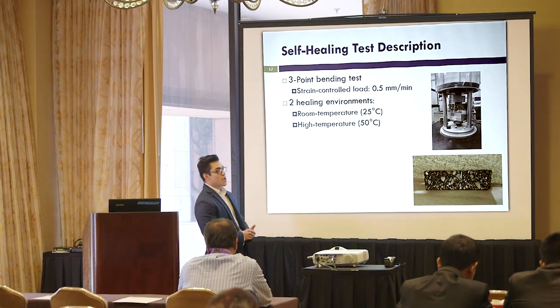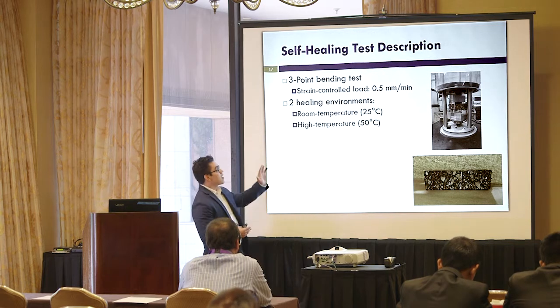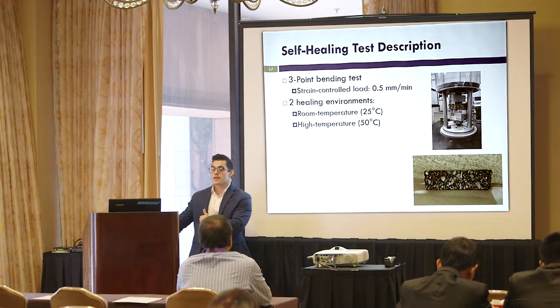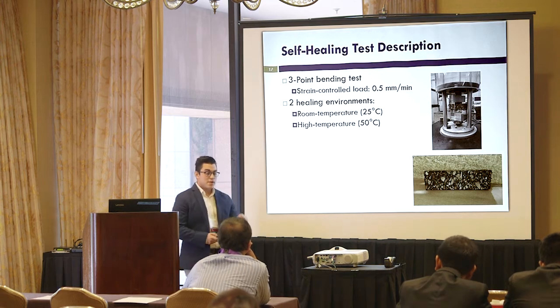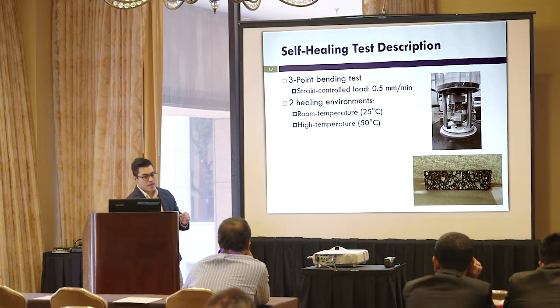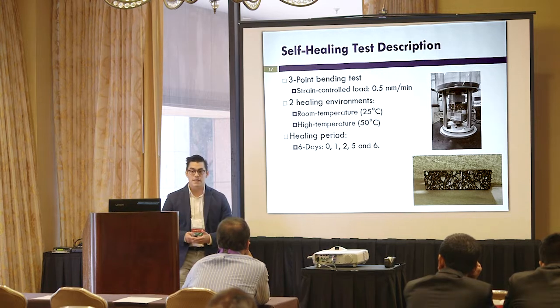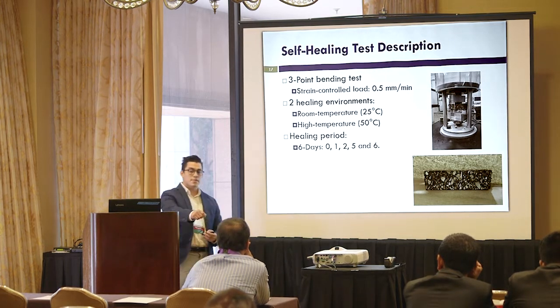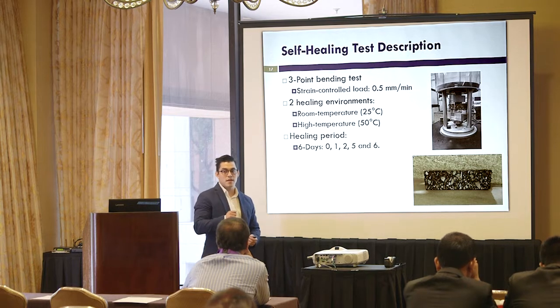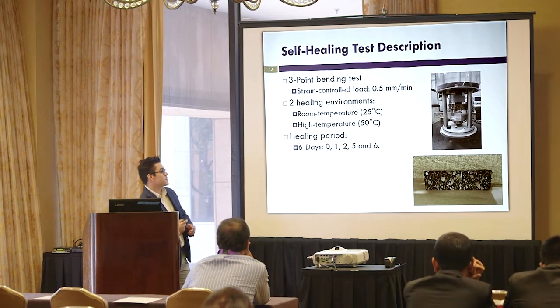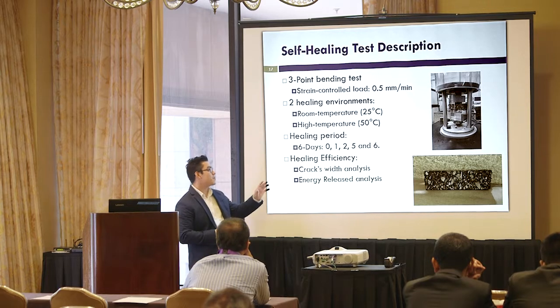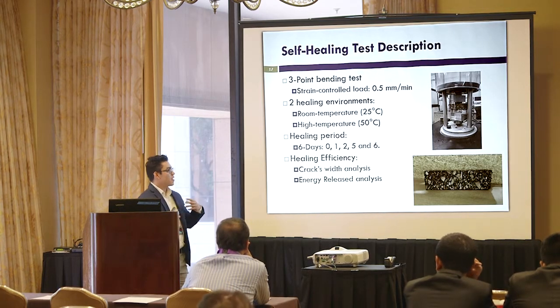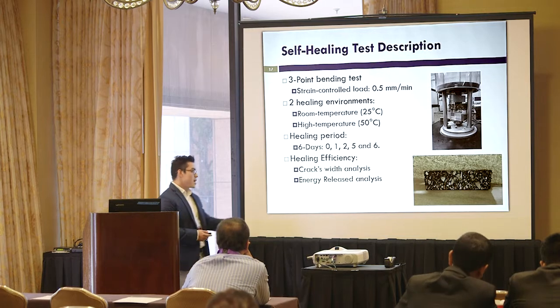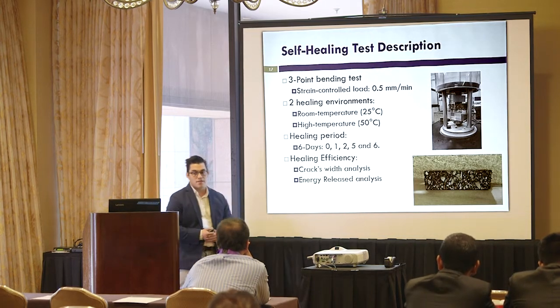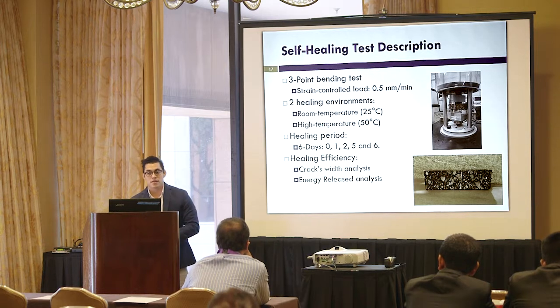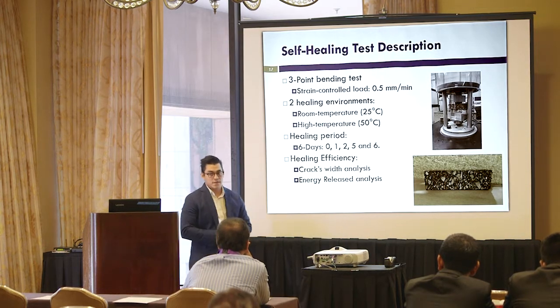and we're going to put some specimens at room temperature, some specimens at high temperature, and we're going to be measuring the crack width every day for 6 days using a light microscope and software image analysis. And that's how we're going to quantify the healing efficiency of these fibers. And also we can obtain the fracture energy whenever we do the three-point bending test.